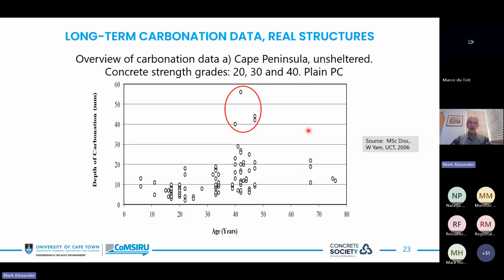First of all, the typical carbonation rate curve is not very clear there at all. And secondly, the carbonation depths are not terribly high. So is that a factor that we need to take into account? Admittedly, this is for plain Portland.